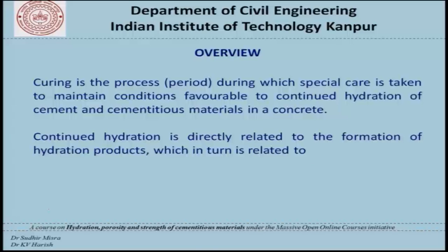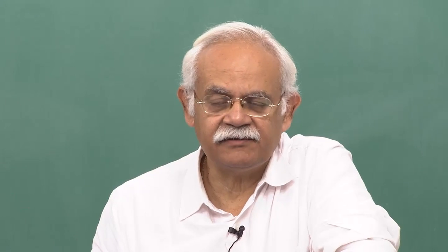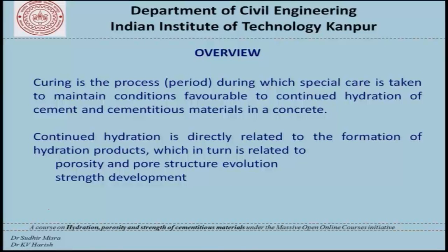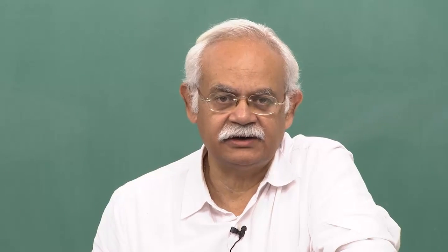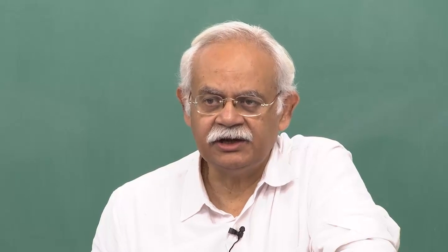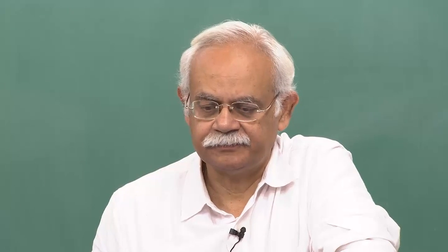Continued hydration is directly related to the formation of hydration products, which in turn is related to aspects such as porosity and pore structure evolution in the hardened cement paste, strength development, whether it is the hardened cement paste or the mortar or the concrete system that we are talking about, and finally durability and permeability related issues. So you must remember at the outset that curing is an extremely important aspect of ensuring durable concrete construction.